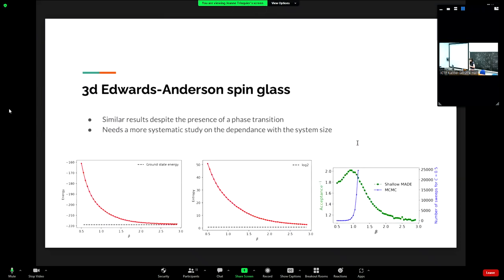We did exactly the same analysis for the 3D EA. Despite the fact that there is actually a phase transition in this model, we found similar results. So a high acceptance rate, we could reproduce the energy and the entropy, we could reach the ground state, and the local MCMC time becomes super slow. Of course we need to do something more systematic on the system size. Maybe these results are not true if you go to large system sizes, but still it shows that for models where local MCMC is not possible, using this strategy allows us to actually sample equilibrium sequences.